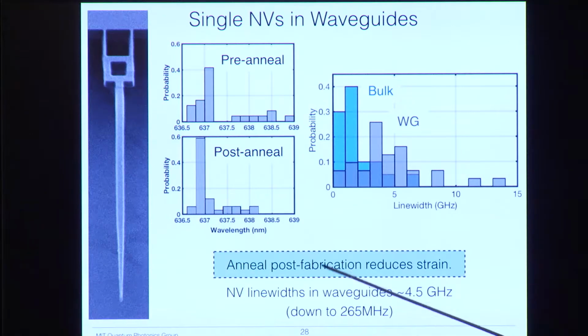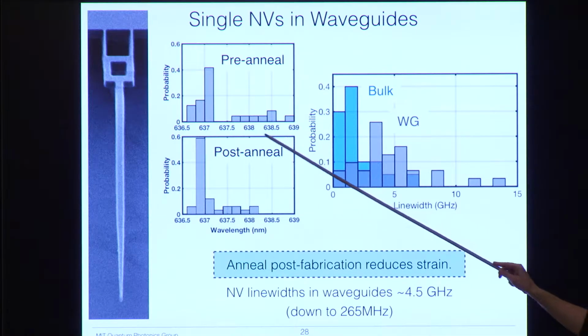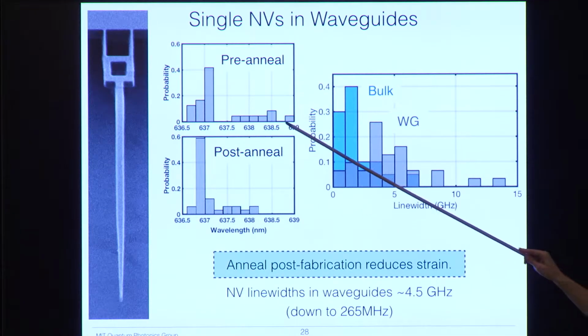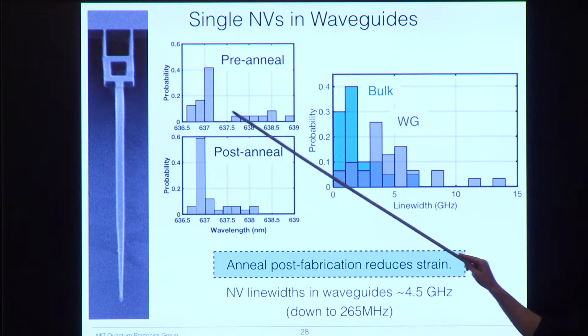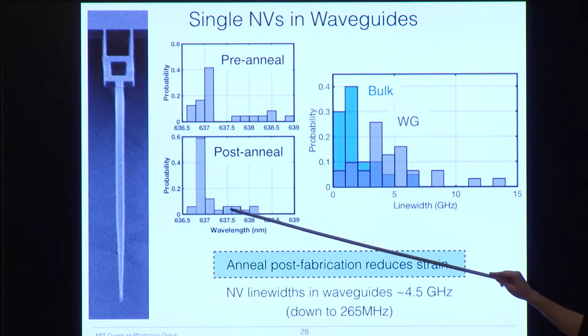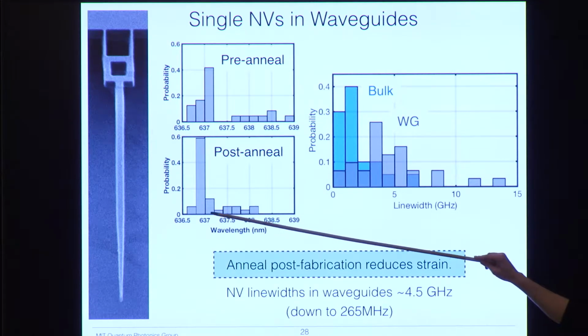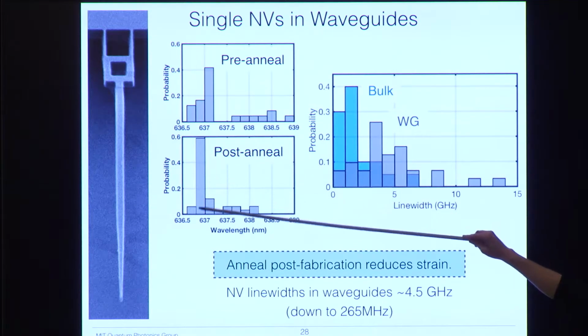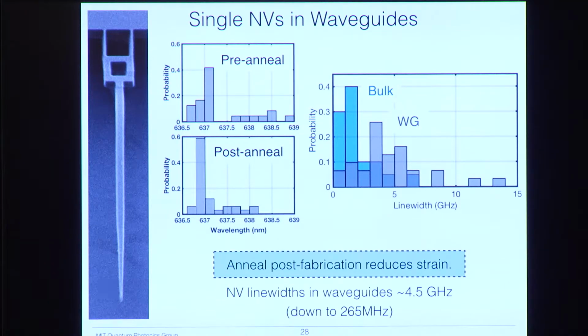So the first thing that we see is, if we look at the wavelengths of all the NV centers that we find before annealing the sample after fabrication, we can see a pretty large spread. After we anneal it, we see that the spread decreases, and most are at where we expect, around 637 nanometers. And so that shows us that we had some strain in our sample that we were able to remove through annealing. So that's a good first step, at least.